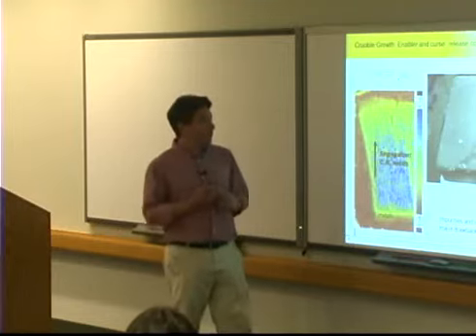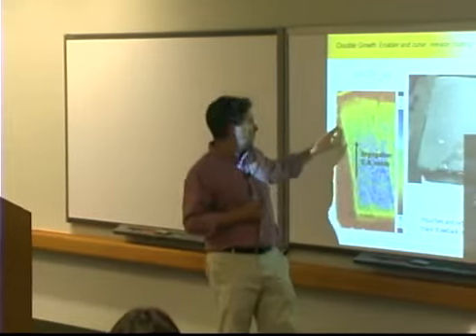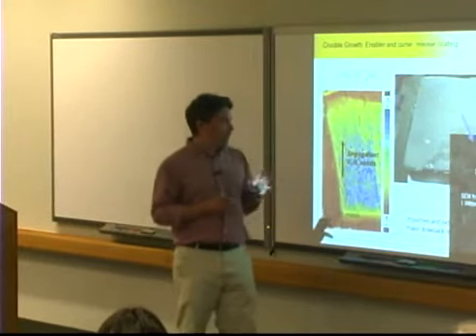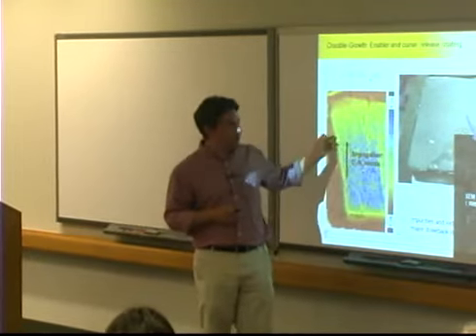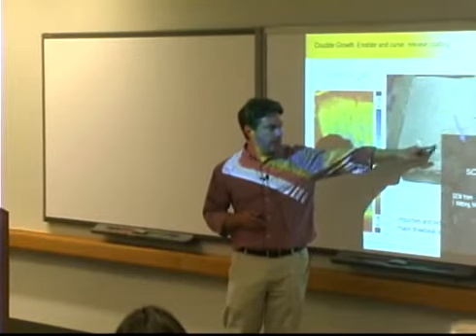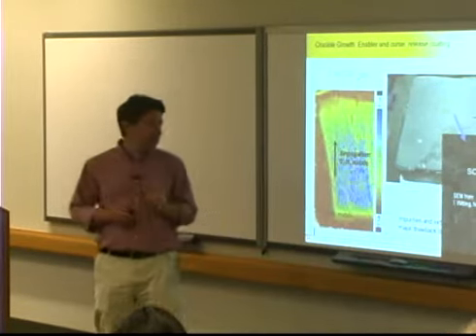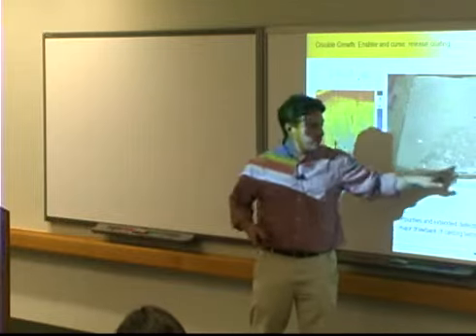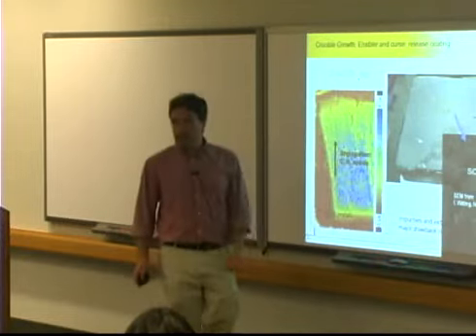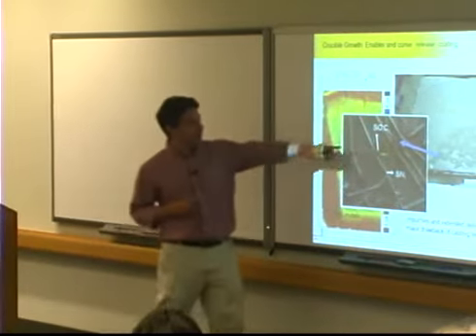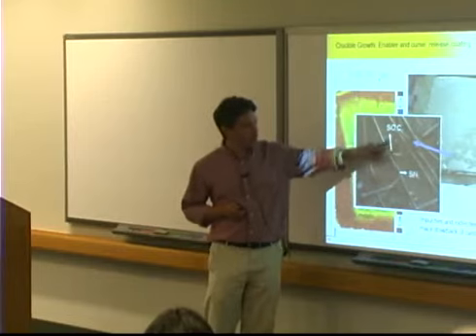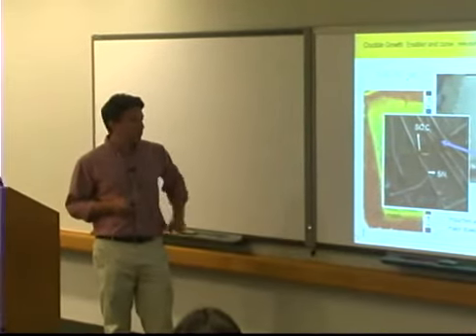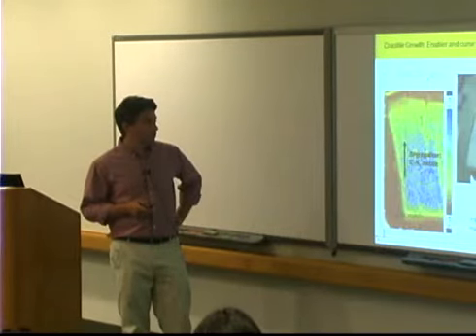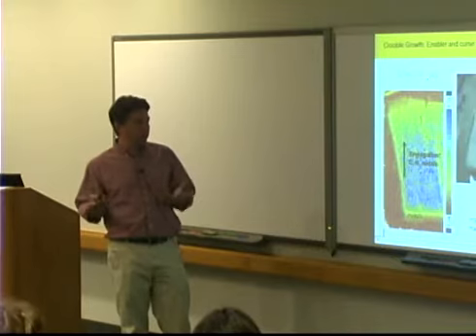And another thing that happens with impurities is that you get carbon, which is kind of from the furnace atmosphere, and then you get nitrogen as well from this release coating, and they move up to the top, but typically form little solid particles, silicon carbide, silicon nitride, and a lot of that ends up at the top. You can see this huge raft of material here. This is all silicon carbide, silicon nitride, and in addition to that, this whole thing is covered in a thin crust of silicon carbide too. And there's some of these silicon nitride needles, and then in dark here, there's silicon carbide kind of platelets and starbursts. So interesting and simple, but kind of riddled with defects.